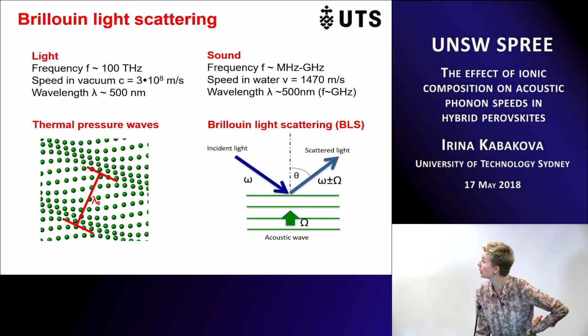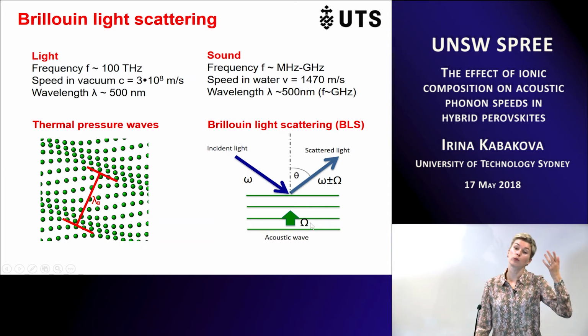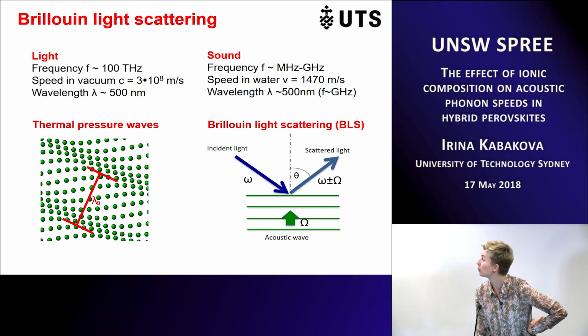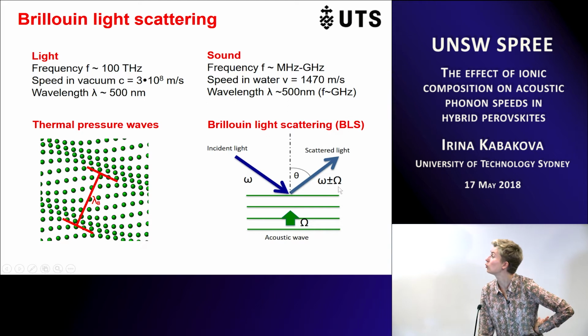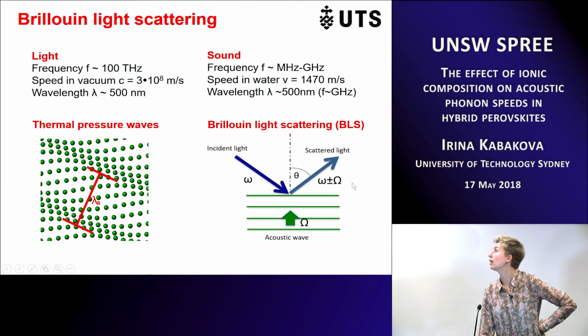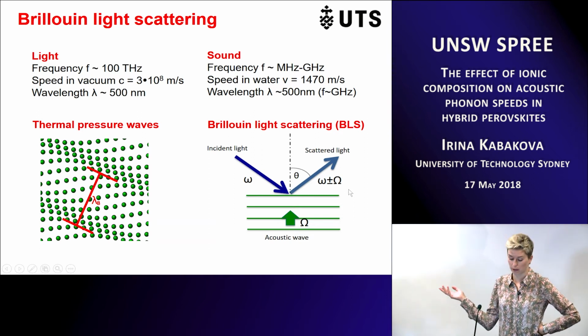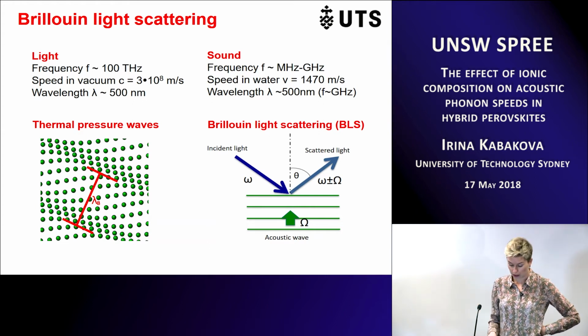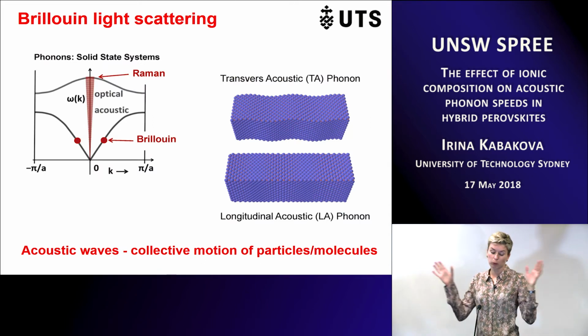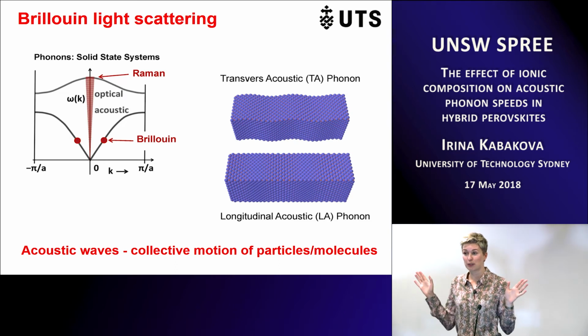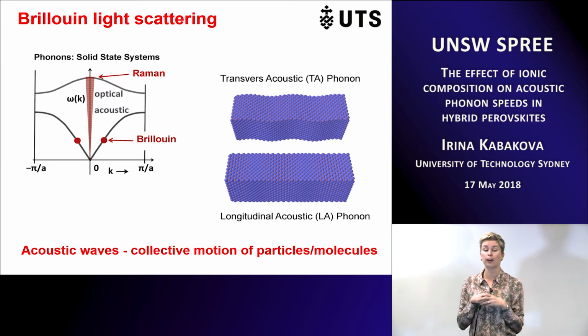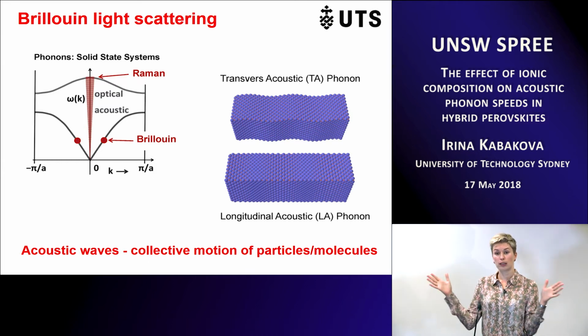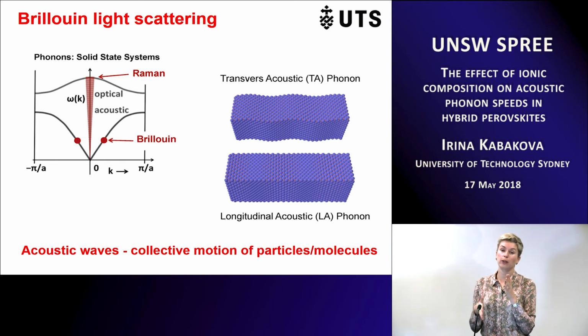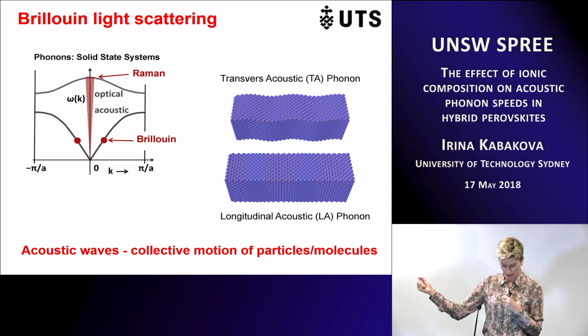And what you get here is that the incident light comes in, meets with an acoustic wave, gets scattered. And because the acoustic wave is a moving wave with a speed of sound, the scattered light loses a little bit of energy or gets a little bit of energy, and this results in a frequency shift. This frequency shift is exactly proportional to the acoustic wave frequency. So what acoustic waves are we talking about? Well, there are plenty of different acoustic waves, but in bulk materials we usually have longitudinal waves, which are a little bit like an accordion, so densification and extension of material, and there are transverse or shear waves, as we call them, where the material moves perpendicular to the propagation direction.